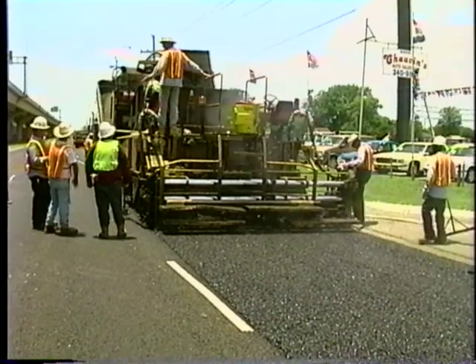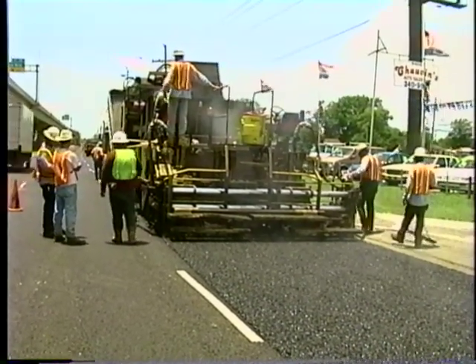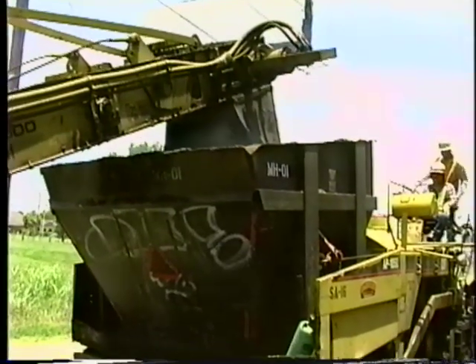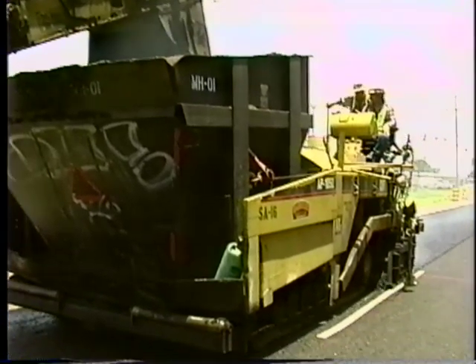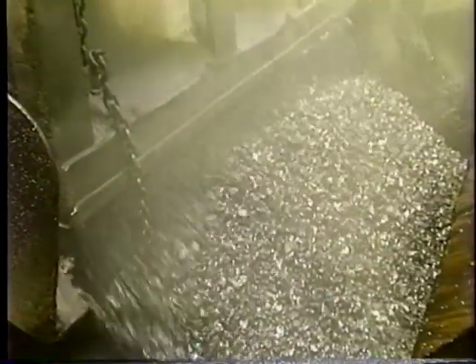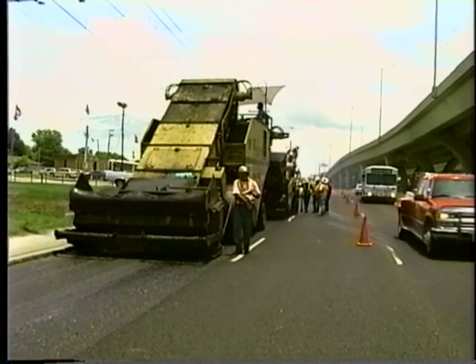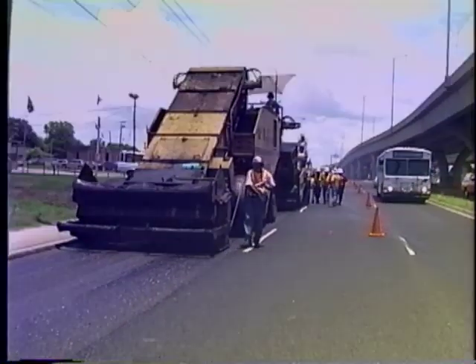Permeability is a very important consideration when looking at hot mix asphalt. A mixture must have air voids that are high enough to prevent rutting. The air voids cannot be so great as to allow excess water into the mixture. If the sample is permeable, then water will enter the mix and stripping will occur.